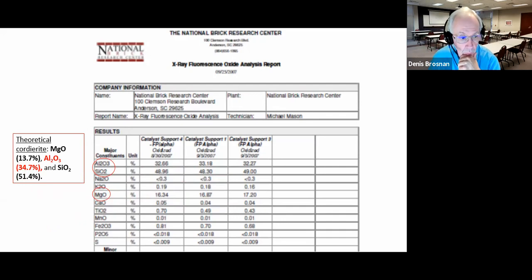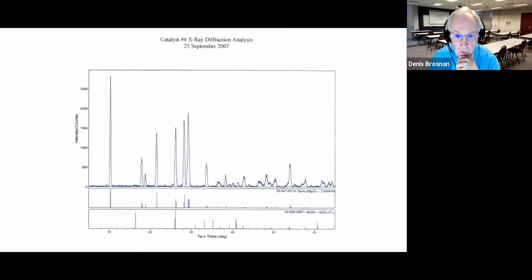And so let's look at the thermal expansion and the X-ray diffraction. And one of these commercial cordierites, like the type of cordierite that Latchman was making, the phases were identified by X-ray diffraction. Remember that identifies the minerals. The phases were identified as cordierite and mullite. Of course, if there's glass present, amorphous phase present, it's not going to identify that.